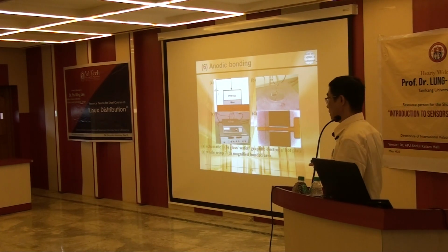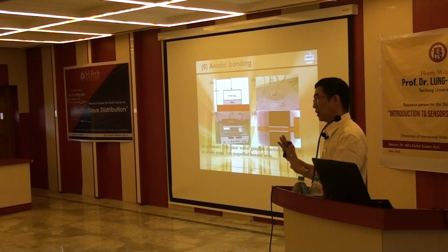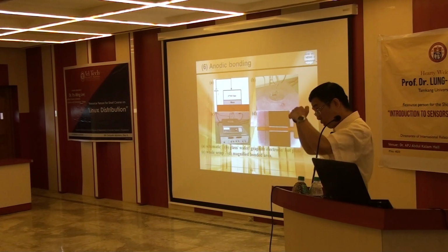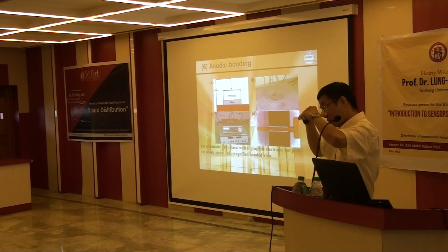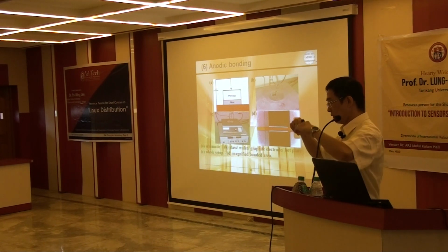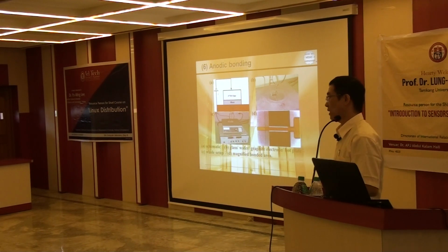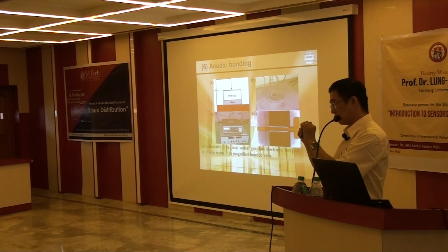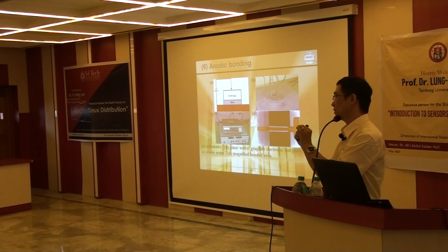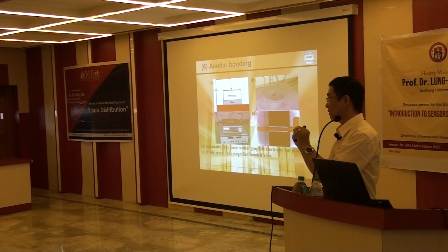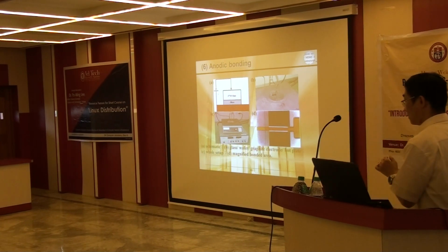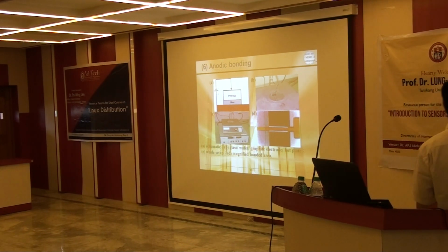The shrinkage of glass and the shrinkage of silicon are different. For Pyrex glass, it's a very strong glass. It will not be broken, but it will distort. Distortion of your specimen is actually no good. Even the inside of the structure has some residual stress due to the thermal mismatch. Residual.